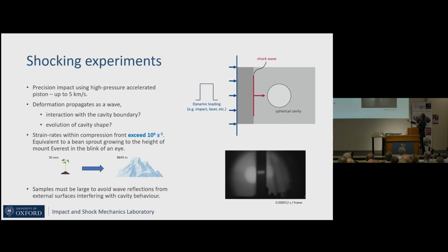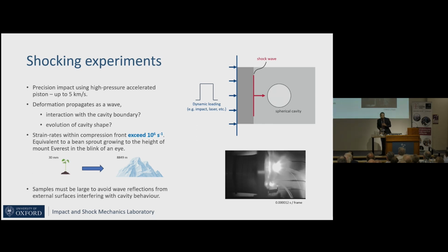But in terms of the conditions that are produced during this kind of interaction, we produce strain rates of order 10 to the 6. That's a big number. What 10 to the 6 represents, if we were to pull on something at 10 to the 6 strain rate, is it would be a bean sprout that was 30 millimeters high, growing to the size of Mount Everest in the blink of an eye. Blink of an eye is a third of a second. So that's quite a severe amount of strain that we're putting in materials.